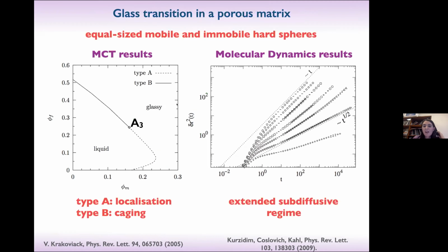And let's start with the canonical case of glass transition in a porous matrix. Here they consider that they have hard spheres, so another modification of the hard sphere model, but in some cases you have fixed particles, and in some cases you have mobile ones. So Krakoviack showed that basically in these MCT results, you also have a higher order singularity by the competition of these two glassy lines. One that is continuous, that is called type A, where basically you go from liquid to glass in a continuous fashion, which means that the plateau of the density correlator does not jump to a high value immediately, but starts from 0. And then you have, and this is a localization transition of the small particle in the glassy matrix of the immobile one. And then here you have instead the standard glass transition.